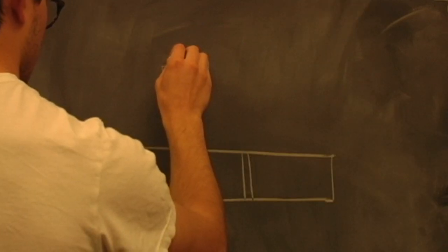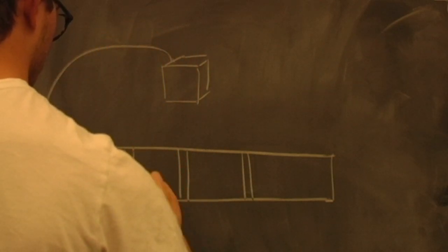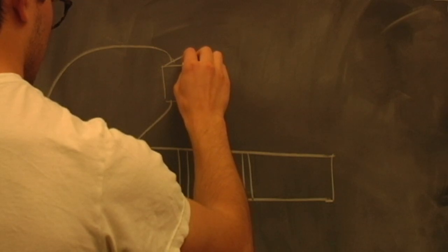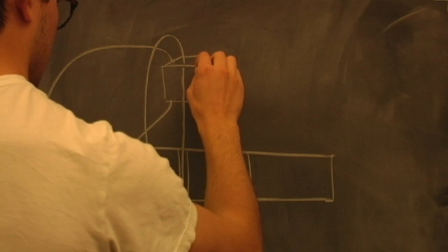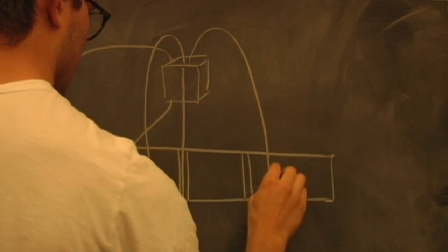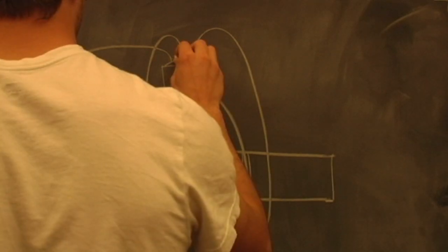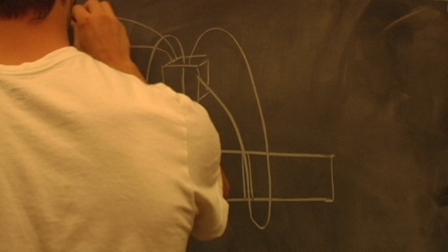How the magnetic field starts to penetrate a type 2 superconductor after it has passed the lower critical field is key to how the magnet can levitate above our YBCO. In 1957, physicist Alex Abrikosov showed that the magnetic field can enter the superconductor in the form of vortices. These vortices consist of a core of normal metal surrounded by a region of circulating supercurrent.